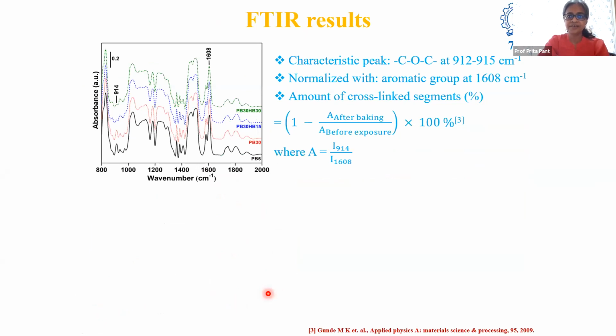So these are our FTIR results. What you're basically looking for is that the epoxy is going to open up and cross-link, right? So as more and more cross-linking happens, that epoxy peak is going to go down in intensity, whereas nothing is going to happen to your benzene rings. So you normalize the intensity of your epoxy peaks with that of the benzene, and that gives you a measure of the extent of cross-linking that has happened. Okay, so that's what we did.